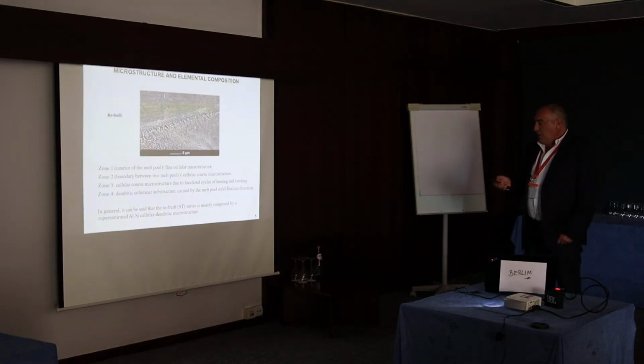So, some results. Here we can see the microstructure of an as-built specimen, typical of this kind of AM material. We have basically 4 zones. Zone 1 is the interior of the melt pool, with a fine cellular microstructure. Zone 2 is the boundary between 2 melt pools, where there is also a coarse cellular microstructure. Then zone 3, a coarse cellular microstructure due to localized cycles of heating and cooling. And finally, a dendritic columnar substructure caused by the melt pool solidification direction. In general, it can be said that the as-built series is mainly composed of a supersaturated aluminium silicon cellular dendritic microstructure.